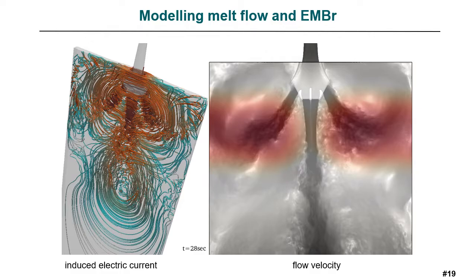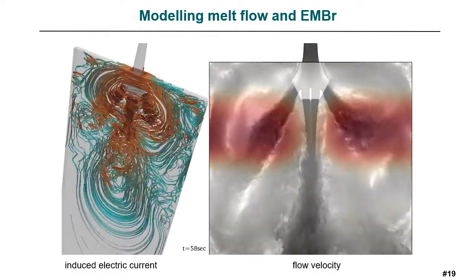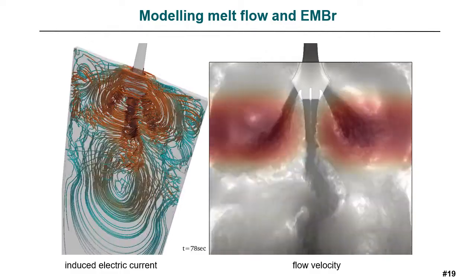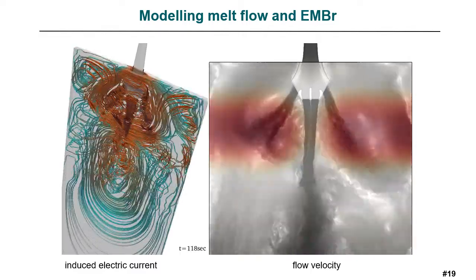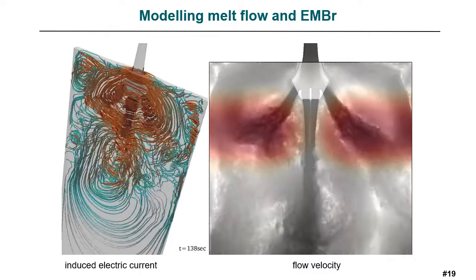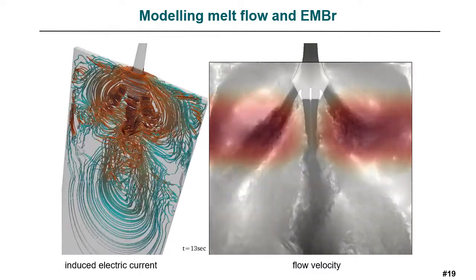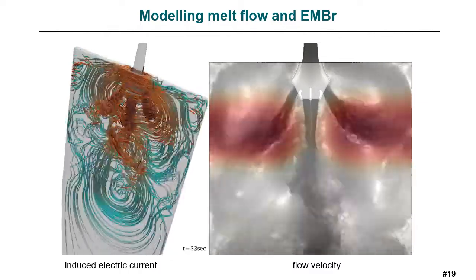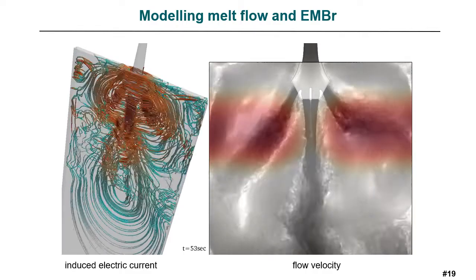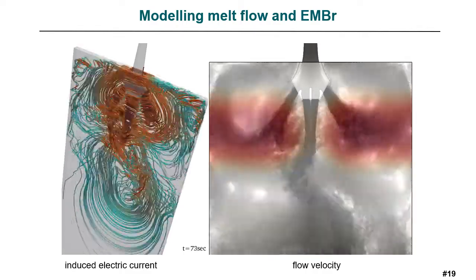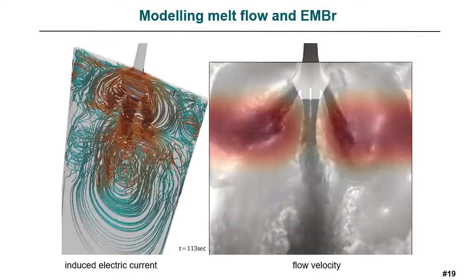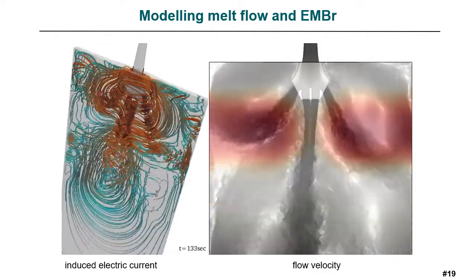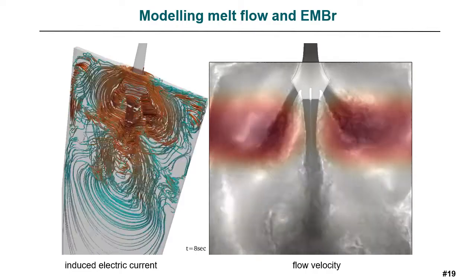Typical simulation results of the MHD flow without considering solidification consists of induced electric current distribution on the left and the velocity field on the right. One can see quite strong damping of the turbulent structures at the top part of the mold, where the magnetic field is the strongest, and bending of the jets to the top surface. However, the flow shows quite unstable behavior.